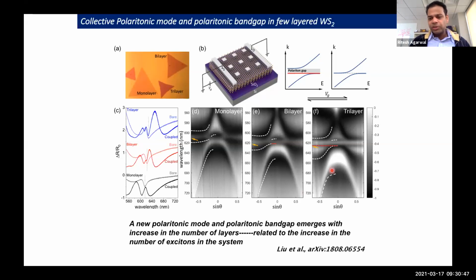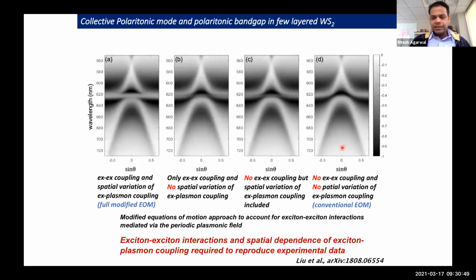It's a very strong coupling strength. And after a lot of simulations and calculations and a lot of experiments, we basically showed that the emergence of the new mode is because of very strong exciton-exciton interactions mediated by this periodic plasmonic field. So again, this is another handle in these two-dimensional materials to reach these very interesting regimes where interparticle interactions can shape the spectroscopy and the response of the system.